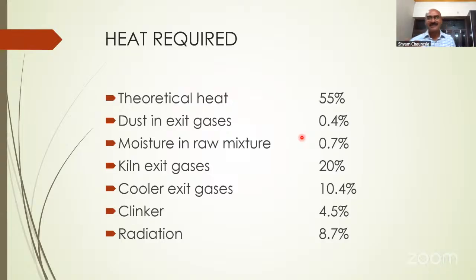As I shared, there are a lot of losses in the refractories, which have been reduced to some level by reducing the kiln size, but still we have radiation losses, dust losses, moisture losses, kiln exit gas losses, and cooler exit losses. Radiation losses are 8.7%. But the major contributions are kiln exit gases and cooler exit gases, 10 plus 20, 30%, plus clinker losses of 4.5% here. So the major losses lie in kiln exit gases, cooler exit gases, and radiation losses.